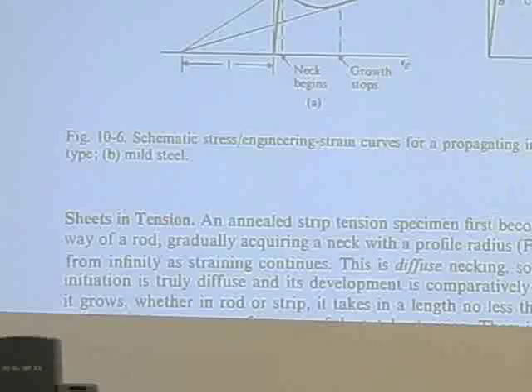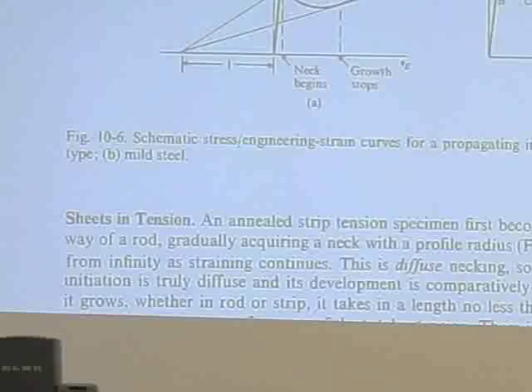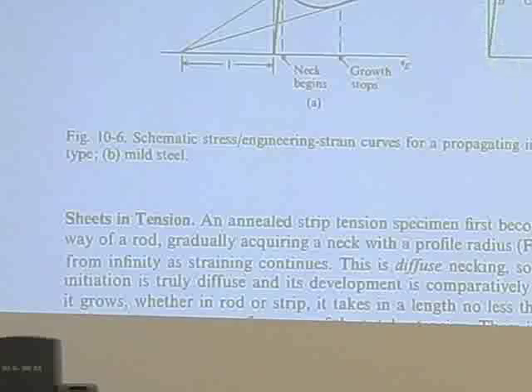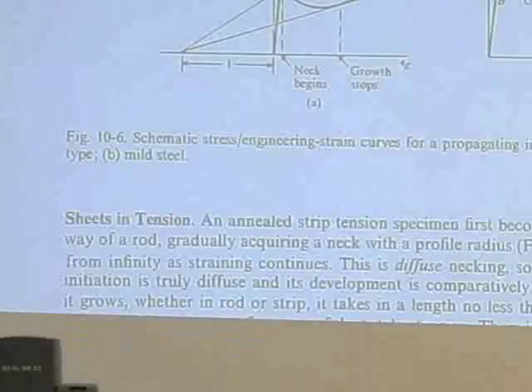In the old days, before 1960, let's say, when we didn't know how to control the steel chemistry so well, we had a lot of nitrogen in the steels, and we would end up with something called the Luder's strain. If you did a tensile test on mild steel, you'd have the upper yield point, the lower yield point, and the Luder's strain, which would actually be a bunch of hash marks in here, okay? It'd be kind of oscillating, but it's basically a constant stress. And then it would start work hardening.